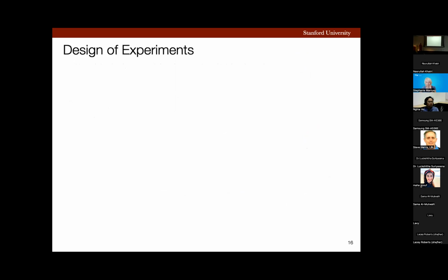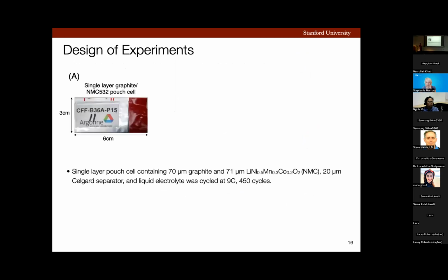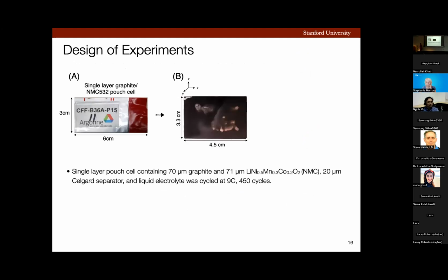My design of experiments for this work included a single-layer battery pouch cell that was assembled by scientists at Argonne National Lab. This pouch cell consisted of a graphite anode, NMC cathode, Celgard separator, and liquid electrolyte. And this battery was charged at 9C, which is around 10 minutes of charging, for 450 cycles. When I opened the battery, I saw these whitish deposits, which correspond to plated lithium.